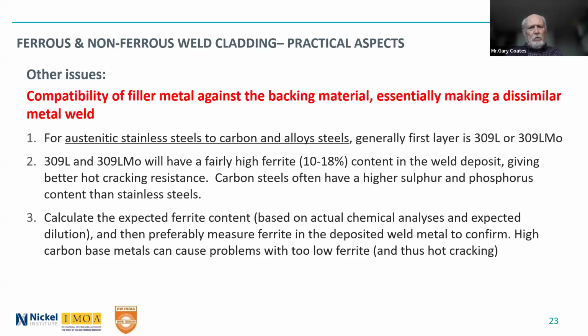The 309L, 309LMo has a fairly high ferrite content, which I'm sure you're well aware of from the weld deposit. It's there to give better hot cracking resistance because carbon steels often have higher sulfur and phosphorus content than stainless steels. So that's a benefit. But as welding engineers, you really need to calculate the expected ferrite content based on the actual chemical analysis, not the typical. You don't want to use that. You want to use the actual chemical analysis of the backing material and the filler metal. So you have to make sure you get the actual analysis for those.